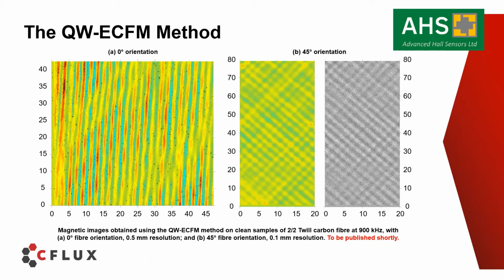The left image shows that fibres that are aligned in the same direction, i.e. 0 degrees, to the linear eddy current region are well detected, since the eddy currents produce a significant response and those fibres perpendicular to the eddy current region are not detected. Moreover, the twill pattern of this sample can be seen in the left image, where the undulations in the weave can be observed, where fibres being woven over the tops of others appear red, with the strongest magnetic field response, and those underneath appear yellow with a weaker magnetic field response due to a slightly larger liftoff. The non-conductive resin matrix is also observed in the background green between the fibres.